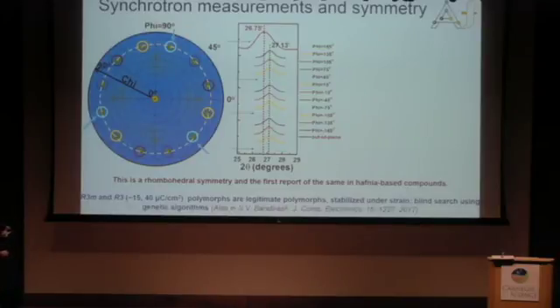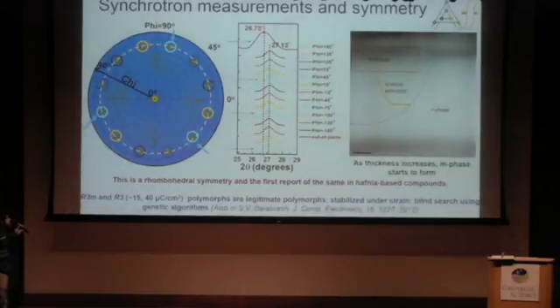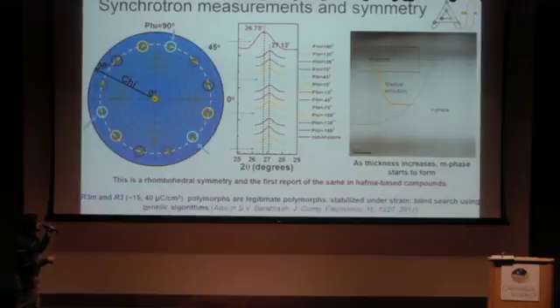So he did find a couple of rhombohedral polymorphs, which can be stabilized under strain using first principles calculations. And the polarizations of the more stable phases are like 15 microcoulomb per centimeter square, actually less than what we measure experimentally. So this is one of the cases where theory is predicting lower numbers than what we are seeing experimentally. Okay, so as you keep increasing the thickness, this picture shows a gradual evolution to the M phase.